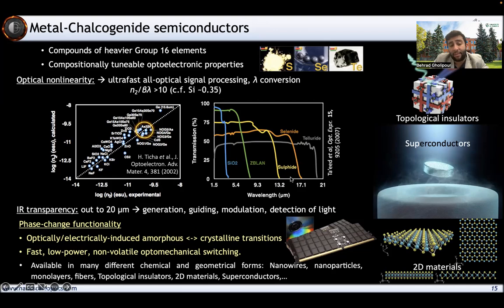They also have very wide transmission windows, so SiO2 ends around just below 5. The sulfides, selenides, and tellurides can stretch the transmission window well into the mid-infrared part of the spectrum, covering the entirety of the telecom band. As I said, the sulfides, for example, many of them are transmissive across the visible all the way to the mid-infrared. That is an unprecedented transmission window that you can use for all sorts of different applications.